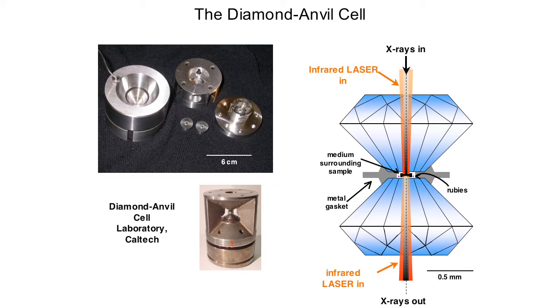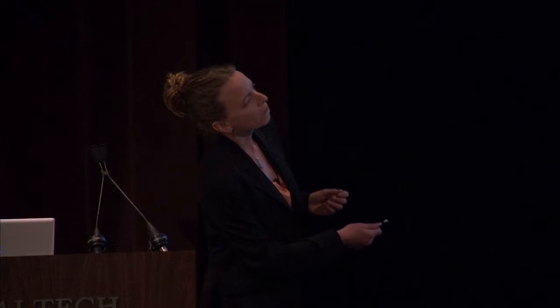So if we zoom in on the sample chamber area, it's a sample that oftentimes we synthesize here at Caltech, and the synthesis is very specialized, so we do that all here. And we place that sample inside of a pressure medium. The goal is to have a very soft environment, as close to hydrostatic as possible, so we can simulate the conditions inside of the Earth. And we place a gasket around that sample, close the cell, and tighten the screws. So believe it or not, pressures of up to 3 to 4 megabars can be generated by these 2 Allen wrenches.